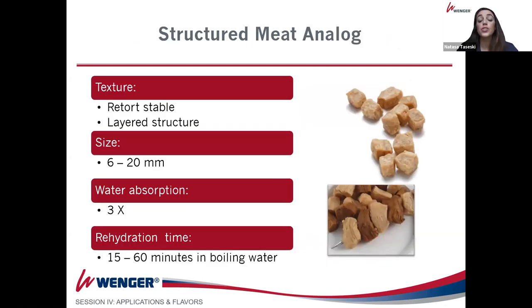Another category is a structured meat analog. This is actually a dense product that, as you can see on the image below the dry product, has a very dense meat-like structure. It's retort stable and has various applications. The only drawback of this product is that it takes a long time to actually rehydrate, but it has decent water absorption and is shelf stable when processed initially.